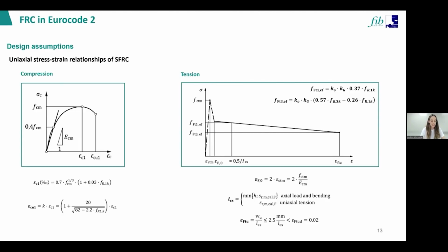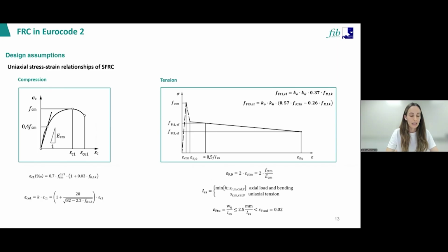In this case, Annex L proposes a simplified three-linear constitutive law, which is capable of reproducing the post-cracking response of the material, including either softening or hardening behavior depending on the residual strength class. The effective value FT1, as you can see on the screen, corresponds to the characteristic value associated with the serviceability residual strength, while the effective value FT3 is obtained based on a moment equilibrium of the notched cross-section.